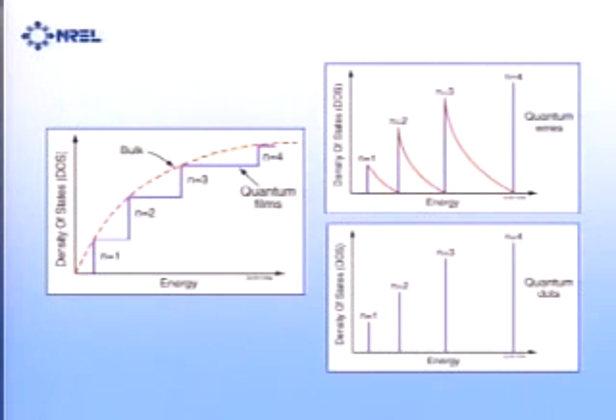not important. And this is where size quantization comes in, because we find that the situation is totally changed now when you go to the quantized regime, which is when you squeeze the electrons and holes into a space that's very small, in the order of the Bohr radius of the electron hole excitonic radius. And as you know, you can confine the electrons in 1 dimension, quantum wells, 2-dimension, quantum wires, or 3-dimension quantum dots or nanocrystals. And this changes the density of states and makes the material look more like an atom than the bulk material, which has a continuous density of states. This will have discrete levels.